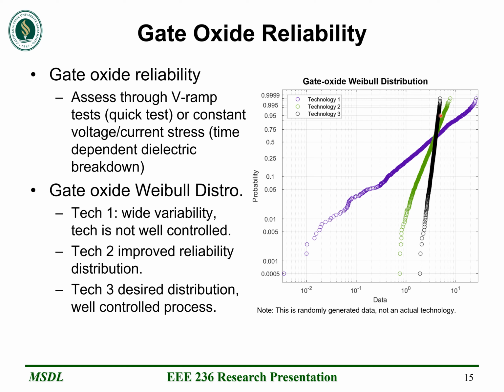Technology 2, while slightly improved, still has an appreciable Weibull slope, but it is better than technology 1. And lastly, technology 3, which is in black, is the more ideal case for a stable process. The oxides appear to rupture roughly at the same voltage or time, which means that the process is well controlled. The ideal case would be a straight line up and down where all of our devices under test, or DUTs, fail at the exact same voltage or time. But again, this is only an ideal case and is not true to the real manufacturing process.